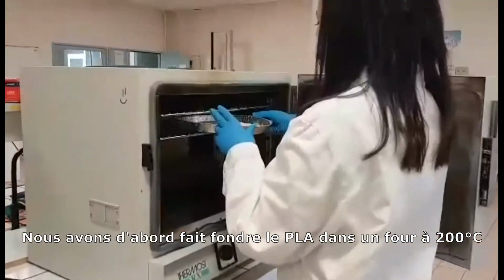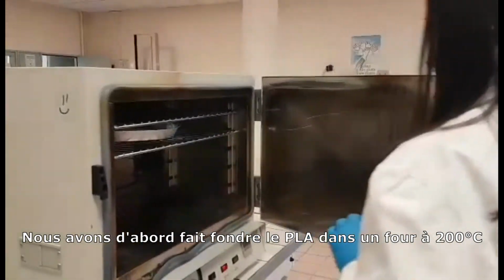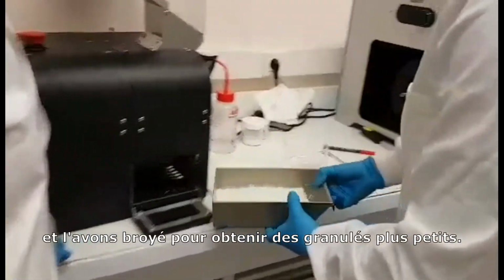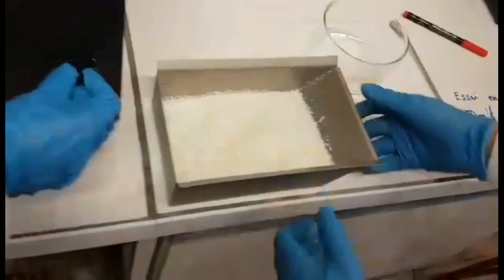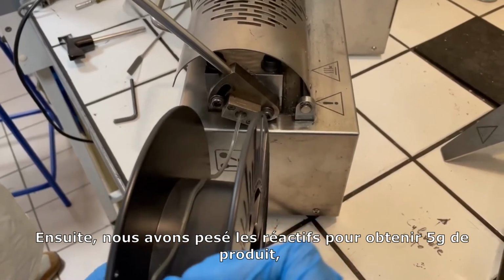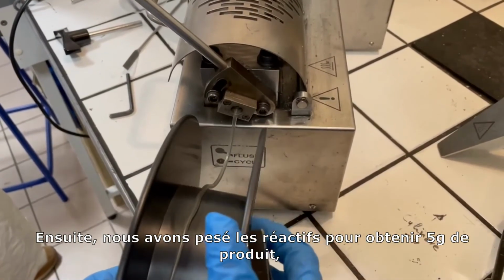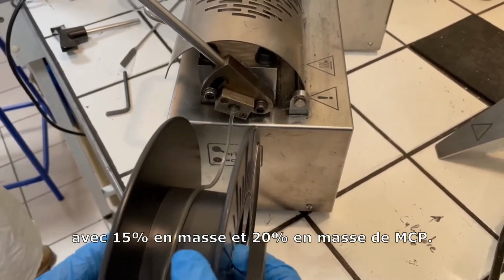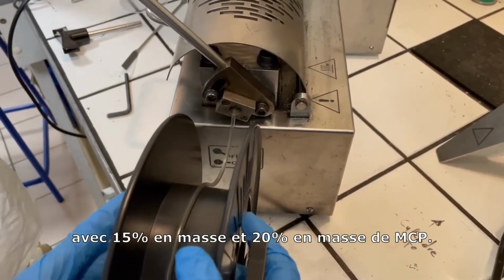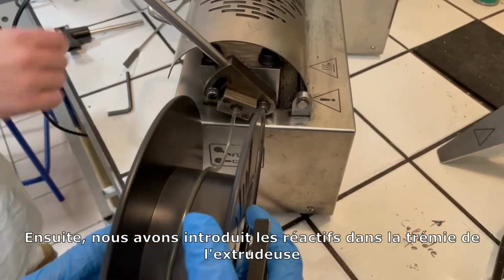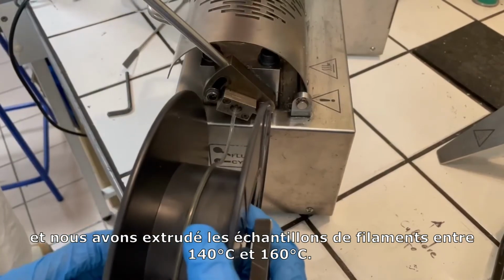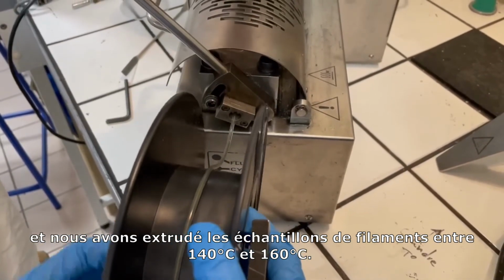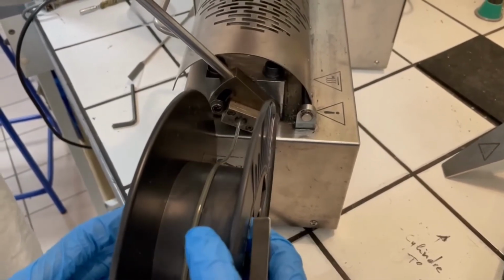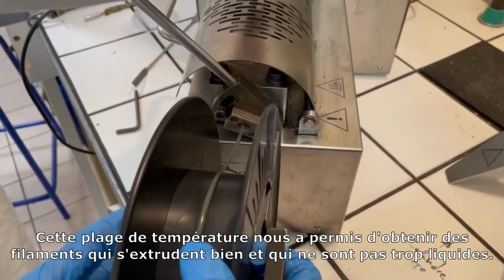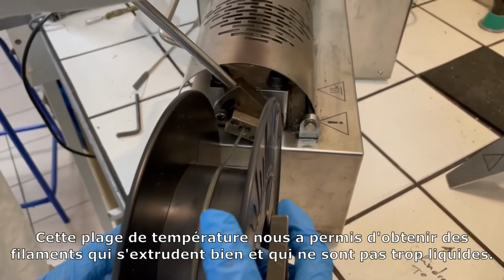We first melted the PLA in an oven at 200 degrees Celsius and ground it to obtain smaller pellets. Then, we weighed the reagents to obtain 5 grams of product with 15% by weight and 20% by weight of PCM. Next, we inserted the reagents into the extruder's hopper and extruded the filament samples between 140 degrees Celsius and 160 degrees Celsius. This range of temperature allowed us to obtain filaments that extruded well and that were not too liquid.